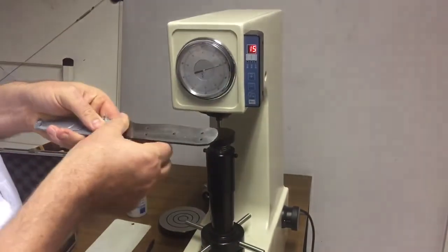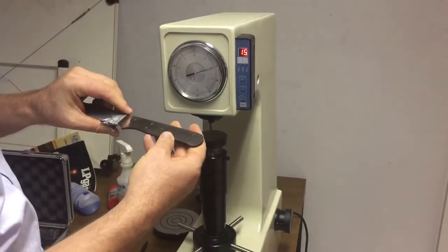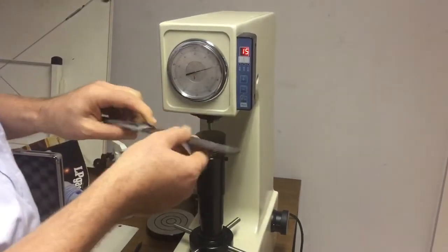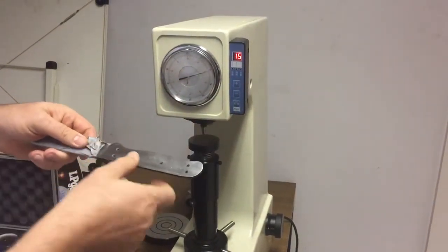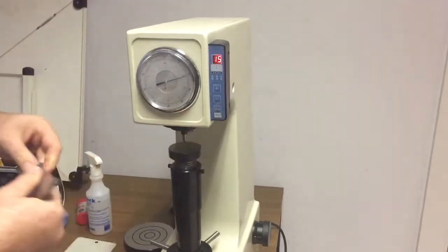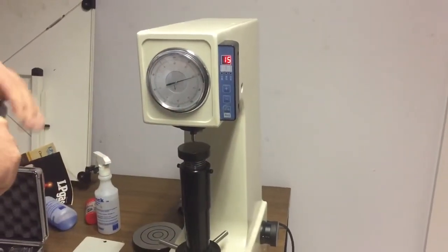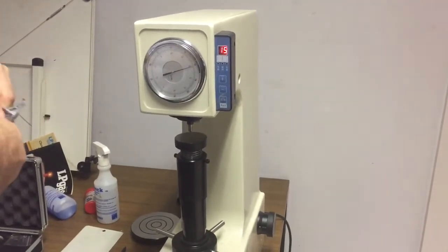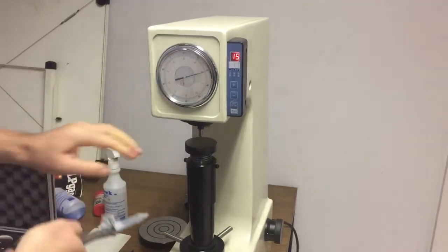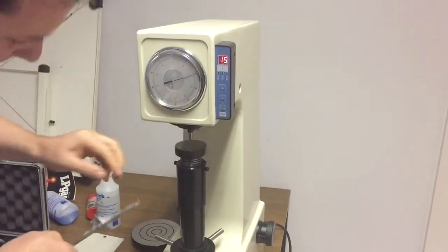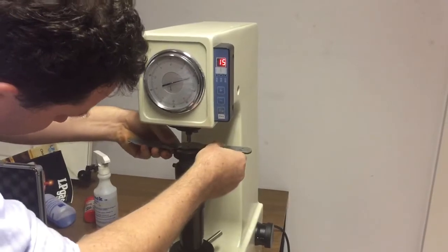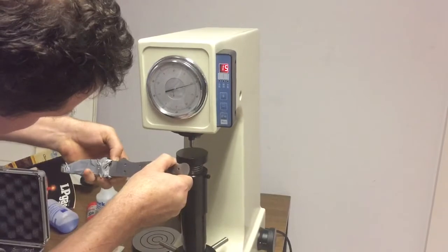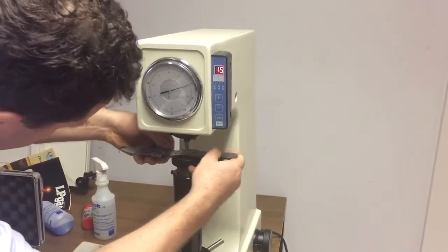This is the customer's blade they've sent in for hardness testing, and we're going to hardness test it now. Hardness testing is going to leave a mark on the blade, so we always hardness test back behind where the scales will be, but as close as we can to the front. Any spot of dust or rust or anything that's on this anvil or on the blade is going to cause a false reading. Just want to make sure that all that material is out of the way.